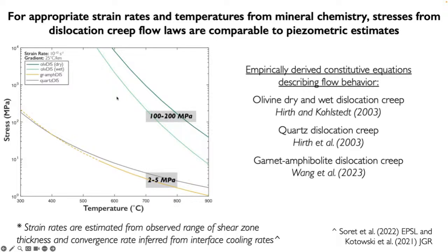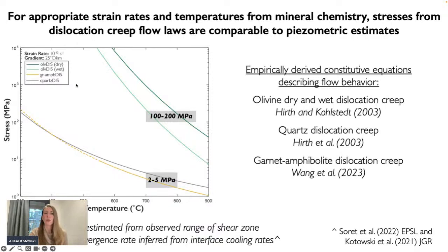So with the convergence rates and shear zone thickness, we can put an estimate of strain rate of about 10 to the minus 13 per second. If we do that and we plot olivine flow laws for the conditions that we know these rocks are deforming at Mont Albert, for example, then we actually get stresses that are quite consistent with our piezometric estimates. So this is very nice. If we play the same game for the metamorphic sole rocks, we get much lower stresses, but still in the ballpark of what we estimated from piezometry.